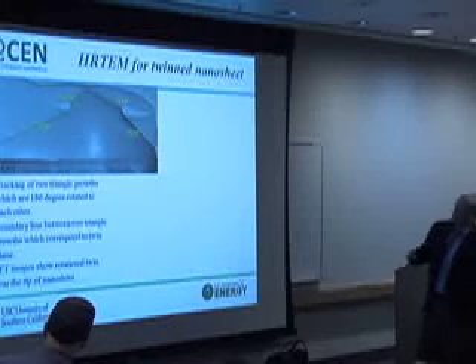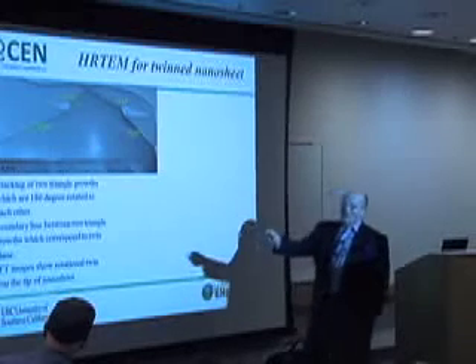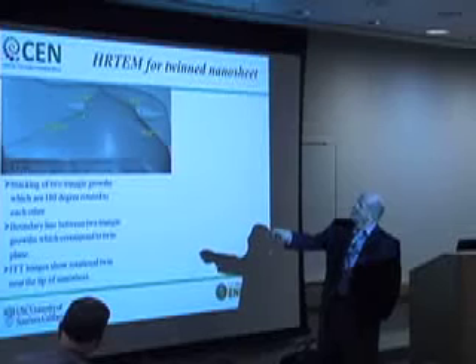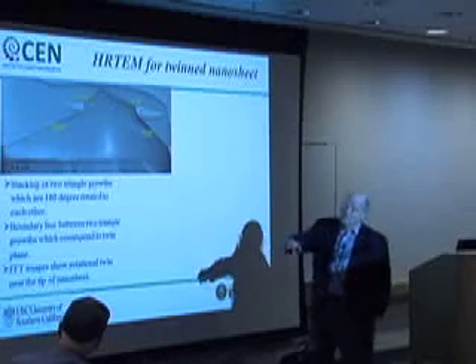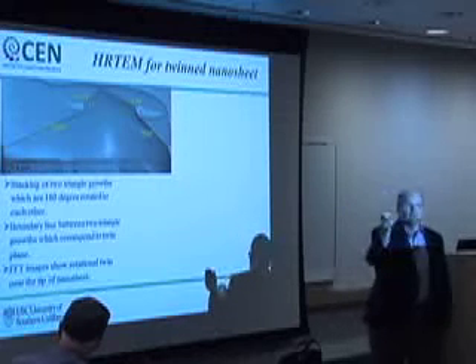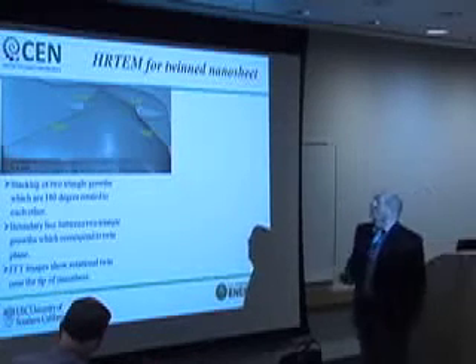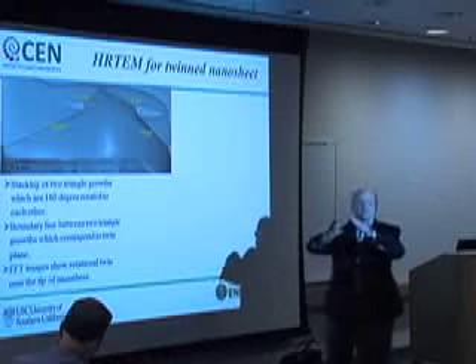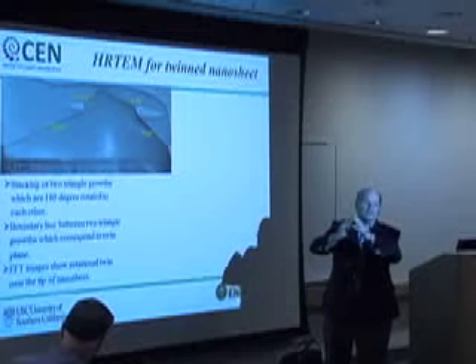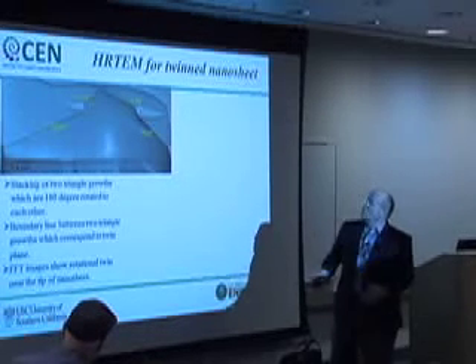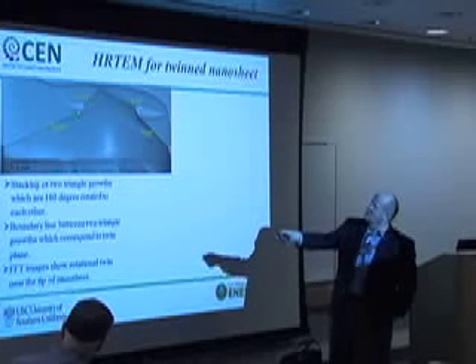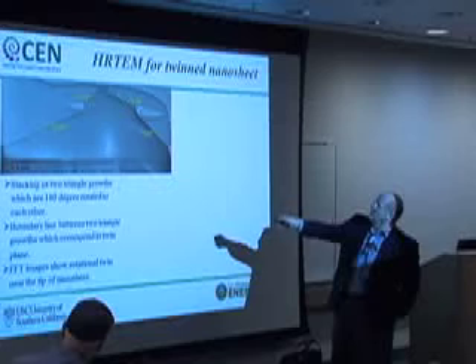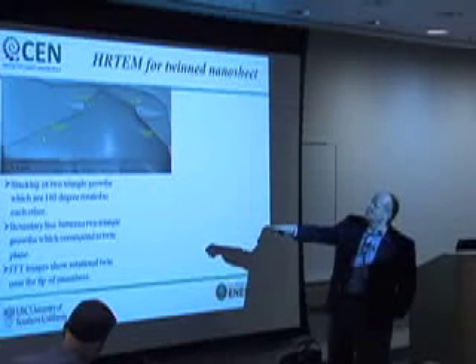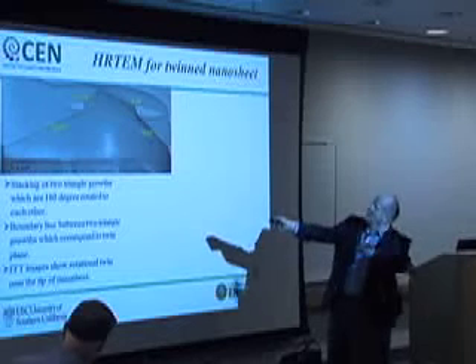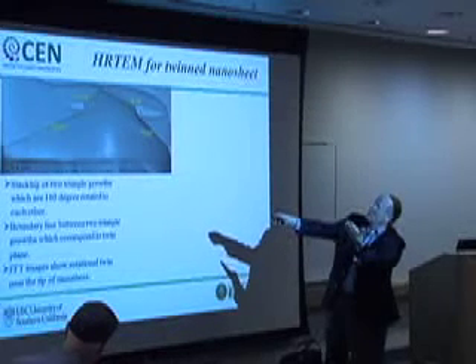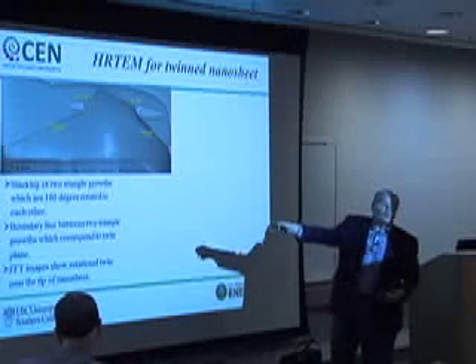See, you're following everything I'm doing here? Well, one of the things that, let me just say, I can't pass this up. One of the things that happens is that when the dimension of this nanosheet begins to approach like 100 nanometers or smaller, about comparable to the thickness of the nanosheet, then the top of that structure looks like an opening in the substrate, and we form twin. Okay, but you only form one twin. So you notice that this thing has these planes that define the angles of the facets here. And once this twin is formed, the thing is rotated by 180 degrees. Now all of a sudden the shallow angle is over here and the steeper angle is over there.